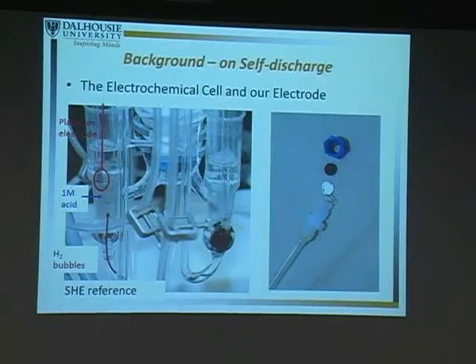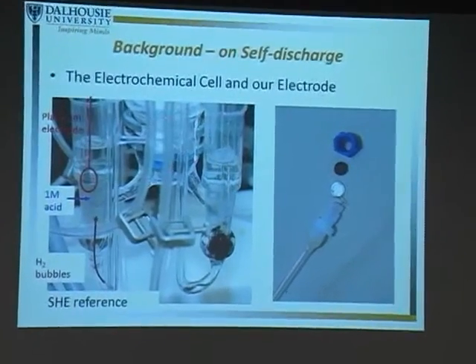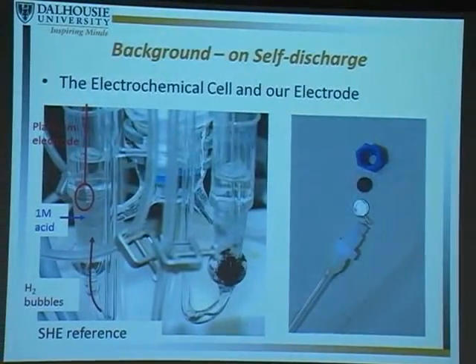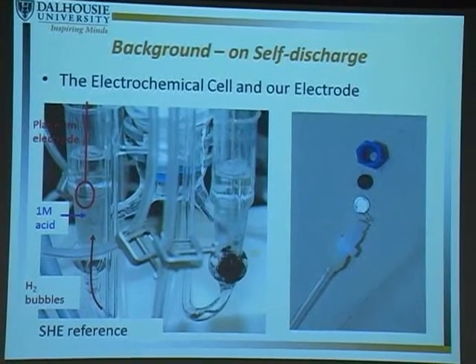For a self-discharge experiment, we ramp the potential at 1 millivolt per second. We sometimes add a hold time, usually 30 minutes, and then we open the circuit and we just measure the potential over time. So this is the cell that we use. It's a three-compartment cell. We have a reference electrode, which is the SHE. We have a big counter electrode, which is a very, very large piece of a high surface area carbon electrode. And then our working electrodes are in a separate compartment, and that prevents contamination between any of the electrodes.